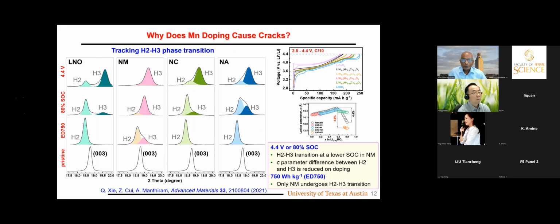Okay, first, you can look here, aluminum is inactive as well, manganese is inactive, cobalt voltage is generally higher, so I would expect nickel oxidized more or less, nickel 3D band is a little bit up compared to cobalt. I would say in nickel cobalt, nickel is largely oxidized, not cobalt, so I don't think the inactivity of the metals is causing these differences, because in all these cases, I think nickel is the one undergoing redox. And then when we dope all these materials, the ionicity, covalency of these bonds may change. There are a lot of things that may go on, which I don't know. You are asking me why it is happening at a lower state of charge. I do not have the answer.